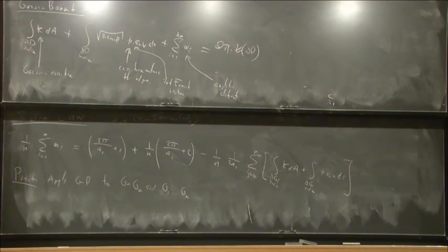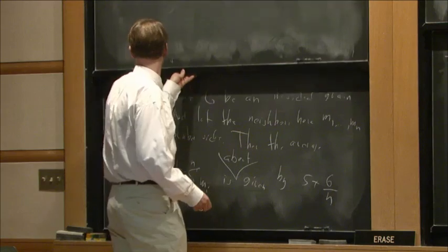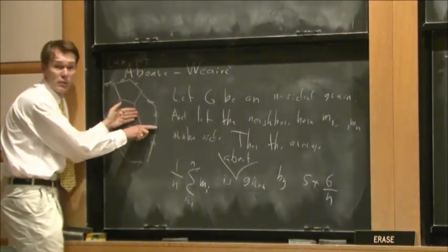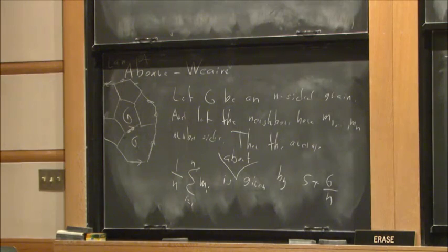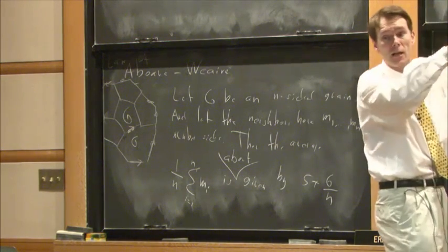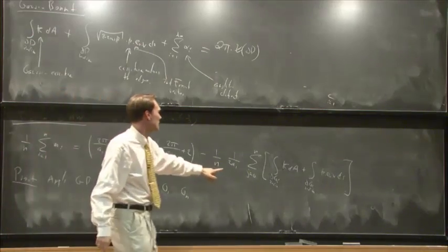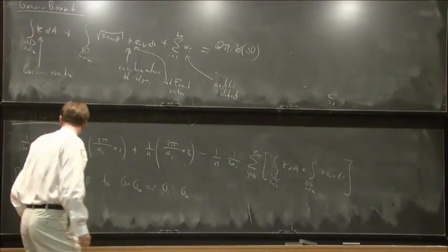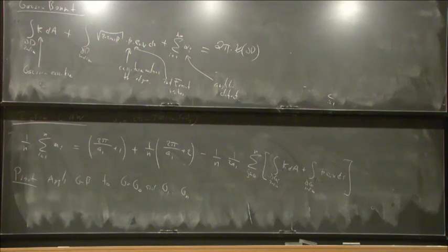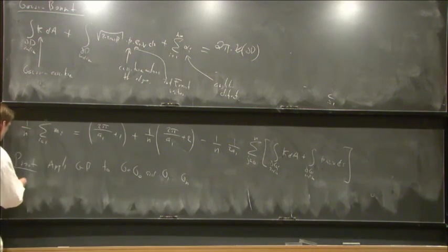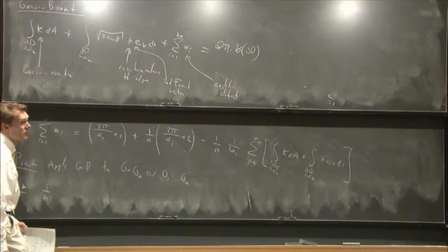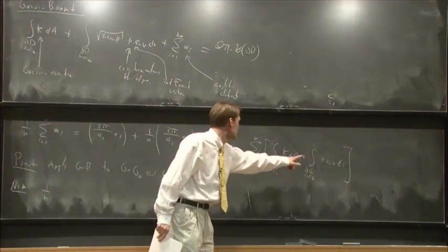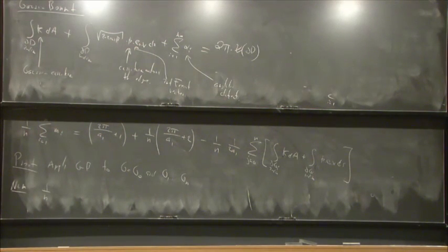So in the two-dimensional case, when we add up the curvatures, they nicely cancelled. However, when you sum up the curvatures here, both the two-dimensional curvature and the one-dimensional curvature, it doesn't cancel out. So the error term here might actually be worse than in the two-dimensional case. In fact, let me write down numerically what it's going to be. You're thinking of that last term as an error term that you want to be small. Yeah, I want this to be small. And in the data Jeremy and Menachem ran on it, it actually comes out to be small, but it's not too bad. Okay?